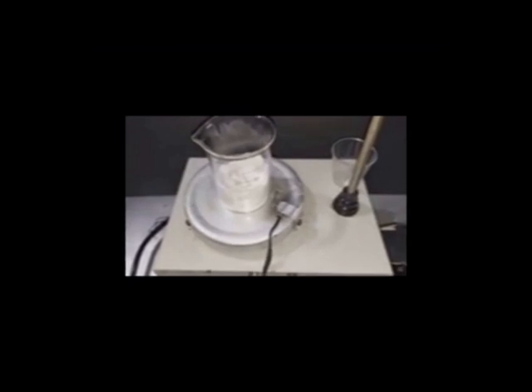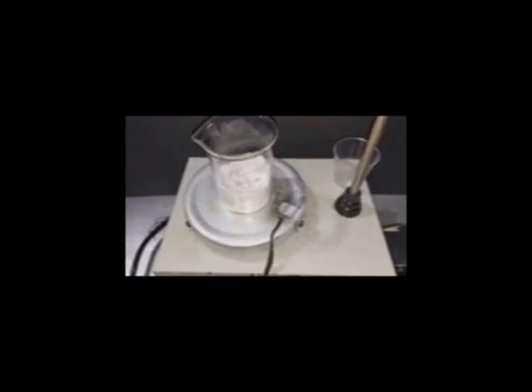The way that it works is our silver nitrate solution that we start with in the silver cells pretty much turns into copper nitrate once we pull all the silver out of it. So we can process 3, 4, 5 kilos of raw silver through this, get our pure silver out. Then we take our silver nitrate solution that's now full of copper, add more copper to it, push the rest of the silver out as a cement silver.